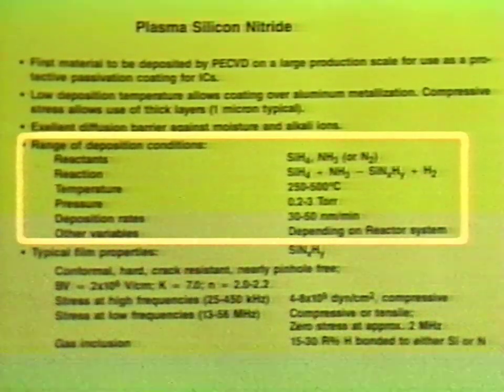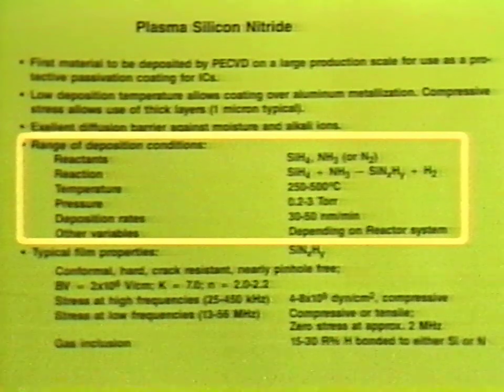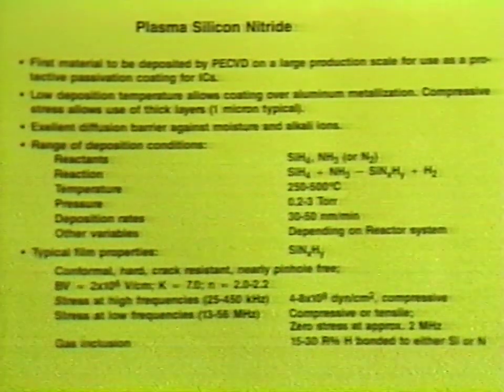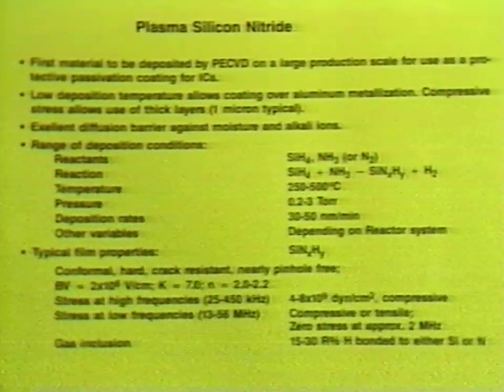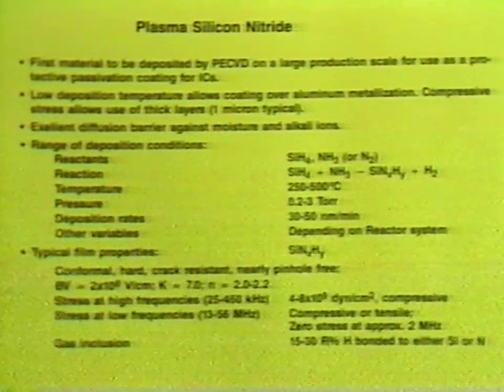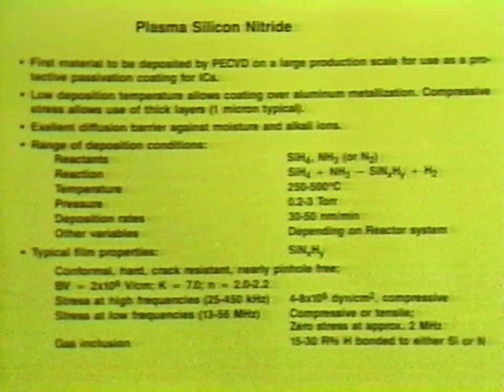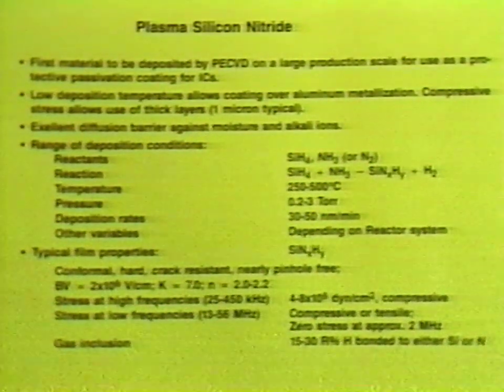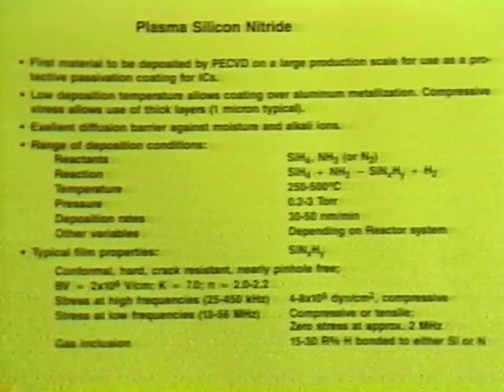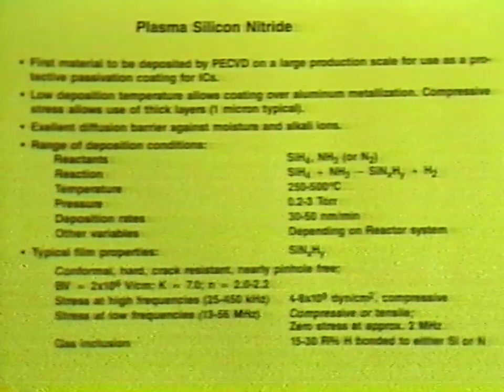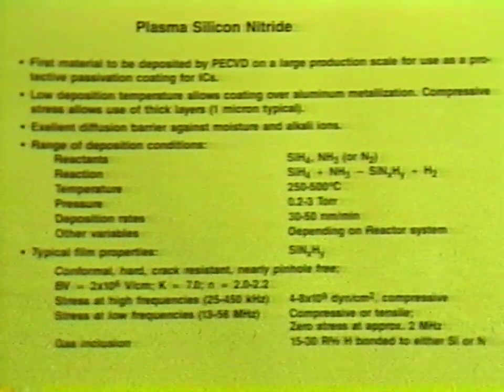We can use either silane and ammonia or silane and nitrogen as the nitrogen compound or nitrogen source. The reaction is indicated there. If we use nitrogen, it is more difficult to dissociate a nitrogen molecule than it is to dissociate the ammonia molecule. So the rates of reactions are lower, deposition rates tend to be lower. And as a result, one prefers in practice the use of ammonia as the source of the nitrogen. And temperature, as I said, temperature range is not critical. Pressure of 0.2 to 3 torr is used in that range. And deposition rates are typically 300 to 500 angstroms per minute, depending on reactor systems.